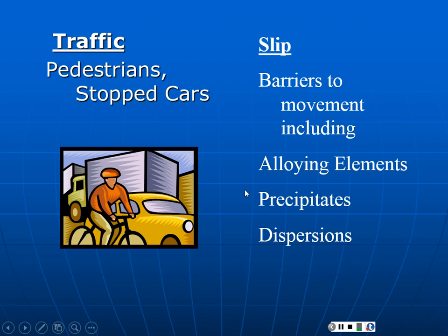We could have alloying elements that, as the part ages, precipitate out of solution and will form small collections of maybe dozens of atoms, very small groups of atoms, not large particles. These are very small. We call those precipitation-hardened alloys. And precipitation hardening is really neat. It's very elegant, but it can be difficult to control the final size of the precipitates. It's very sensitive to thermal history and to age.